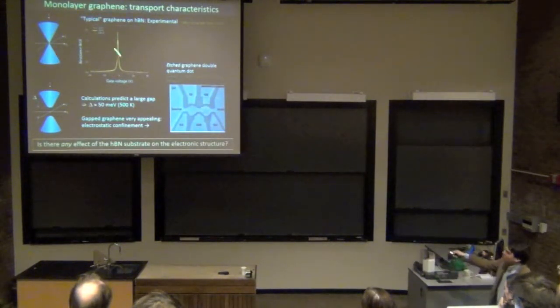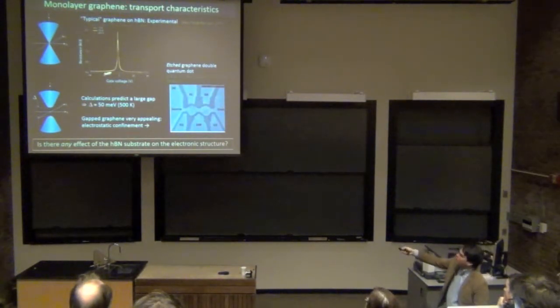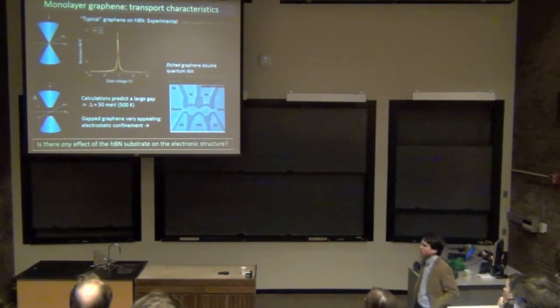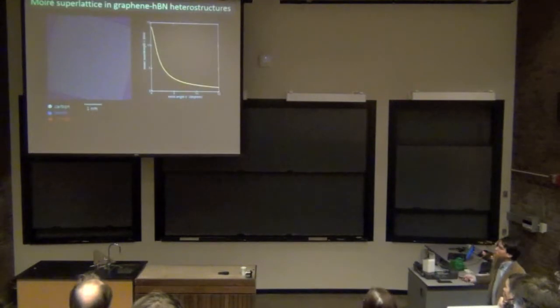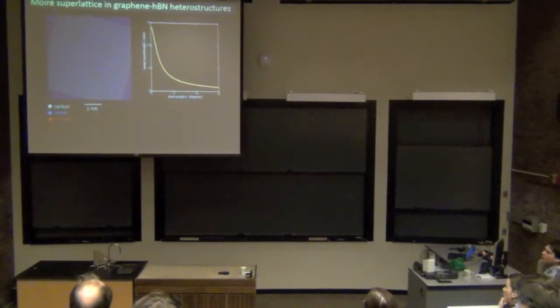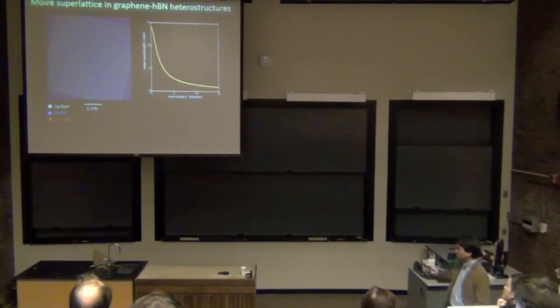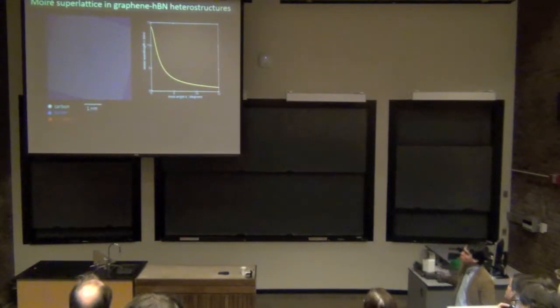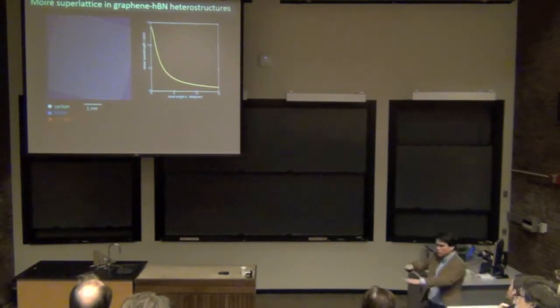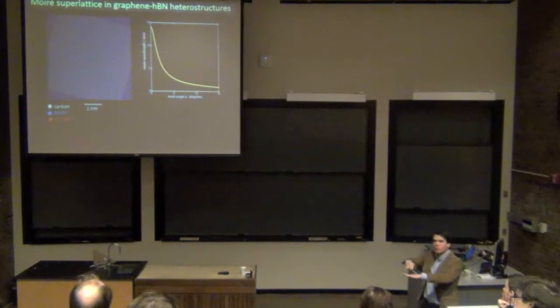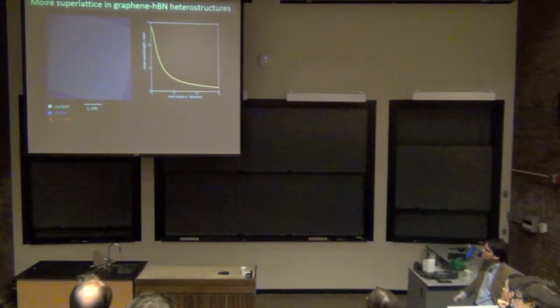So what's the answer? Is there any effect whatsoever of this boron nitride substrate on the electronic structure of the graphene? It looks like from this example that there isn't, but the theory predicts that there should be. So what's the answer? The answer is that it depends. And it depends on an additional degree of freedom that we have in the system, which is that we can twist one graphene layer with respect to the underlying boron nitride substrate.